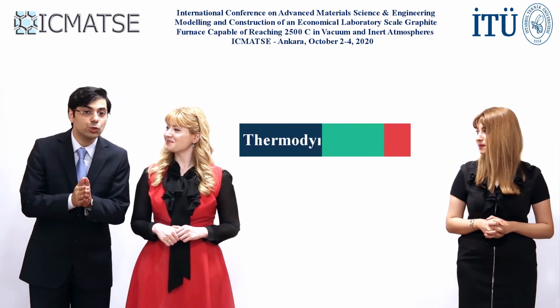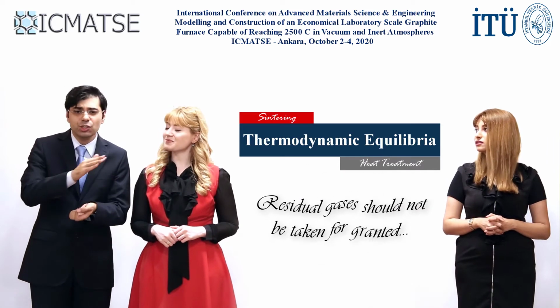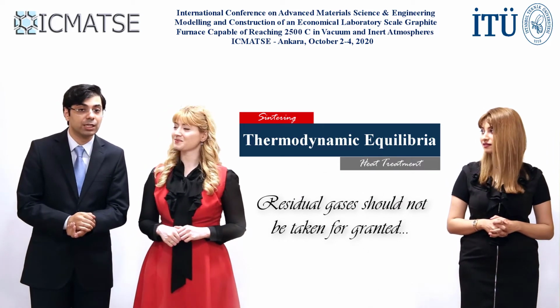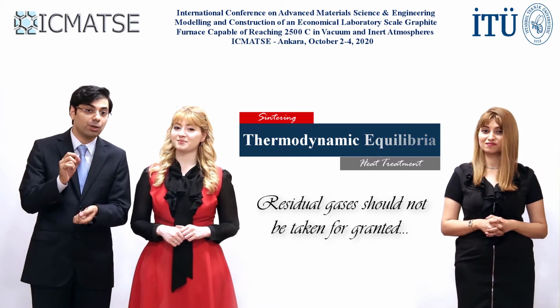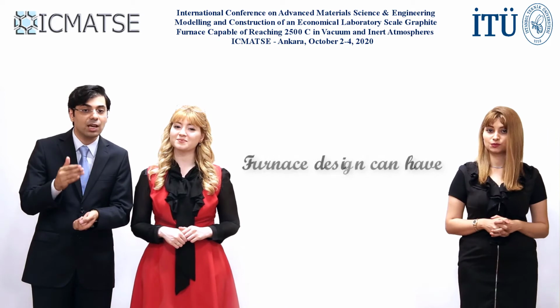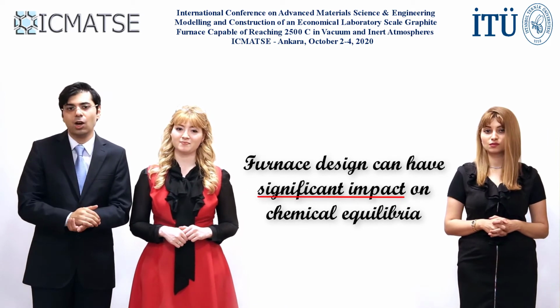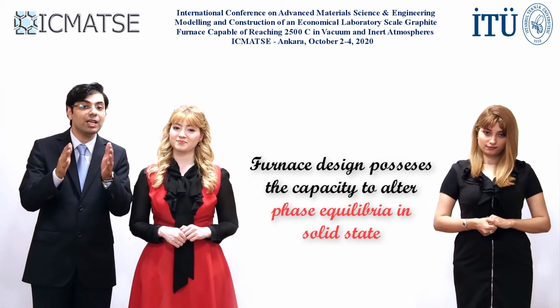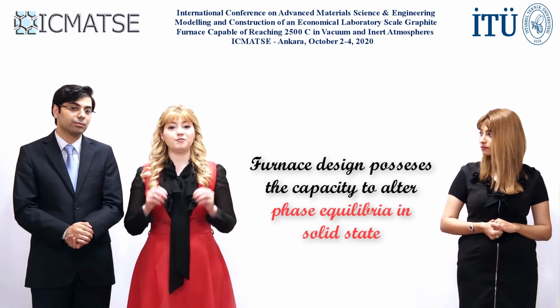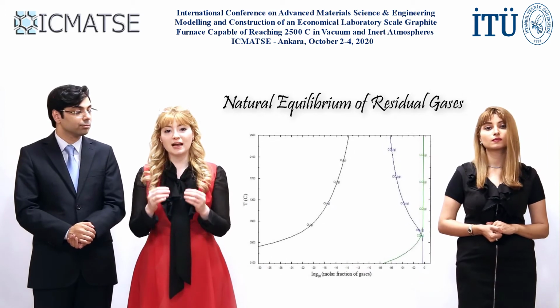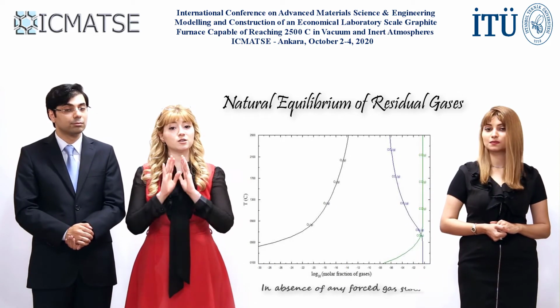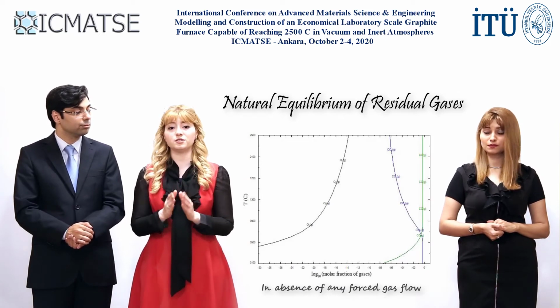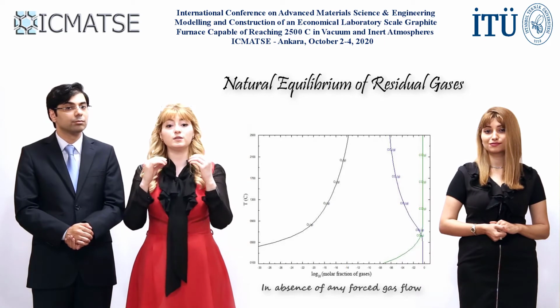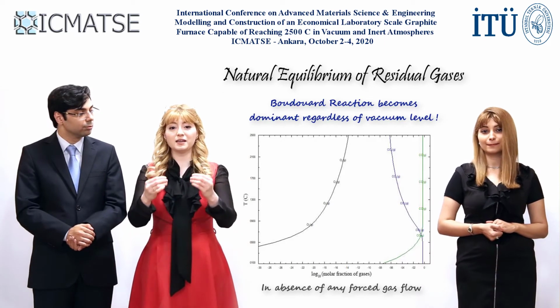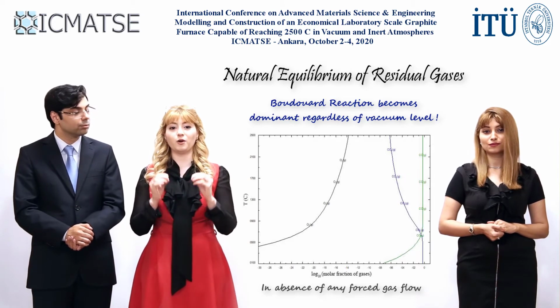On a different note, one should consider the thermodynamics of a system in which any sintering or heat treatment is to be conducted. It must be very clearly analyzed prior to any experimental work, as the furnace design in itself can have significant impact on the chemical equilibria which emerge and also possesses the capacity to alter the phase equilibrium in solid state. Therefore, we have done thermochemical simulations of the natural equilibrium of gases in the furnace in absence of any forced gas flow, because even under such conditions, the thermochemical equilibrium as a result of the Boudouard reaction can quickly become dominant in a graphite furnace, either in vacuum or inert atmospheres.